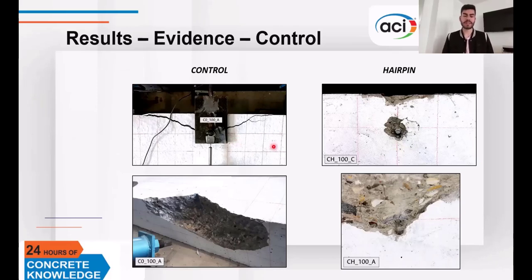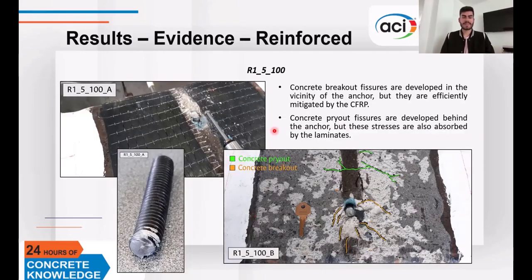Now here are some pictures. On the left you can see the breakout body of the control specimens. On the top right side we have the pure anchor rupture that I mentioned before on the hairpin specimens, and on the bottom right side we have the breakout then rupture failure mode, which was observed in all the other hairpin reinforced specimens. These are the total area concentrated in one laminate on each side specimens. You can see the shear rupture of the anchor and the formation of concrete breakout and concrete pry-out cracks, which did not propagate far from the anchor, as the tensile stresses were effectively taken by the CFRP.